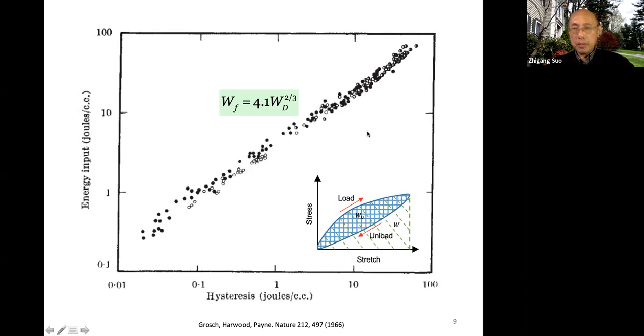These people tested many materials. They published a paper a long time ago in Nature. They said these two quantities, the work of fracture and the dissipated hysteresis energy, are correlated. So when your hysteresis is big, you have a very big work of fracture. If your hysteresis is low, like going up and going down along the same path, you have very little toughness. This view was unchallenged for many decades. I don't know, Thomas, if you teach fracture mechanics, you probably keep telling students, I tell students too, if you want a highly tough material, you want a highly dissipative material. We keep perpetuating this view published in Nature and held strongly by most engineers and people on the street. That view turns out to be wrong. This is what I'm going to tell you.